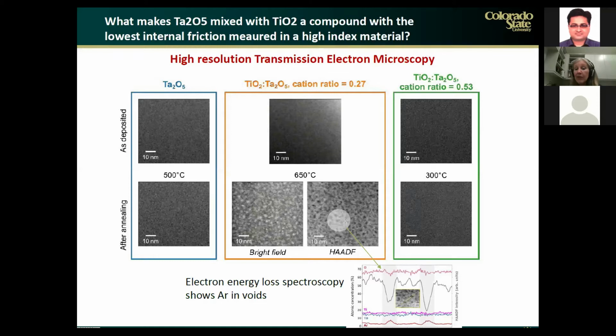and that are voids. So we conducted EELS spectroscopy on these samples, and what we found is that indeed the dark spaces are voids, but these voids actually contain argon. So this, again, is a very special morphology that is obtained right before the material crystallizes.